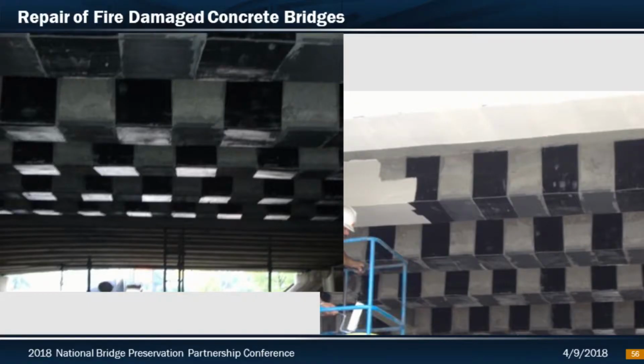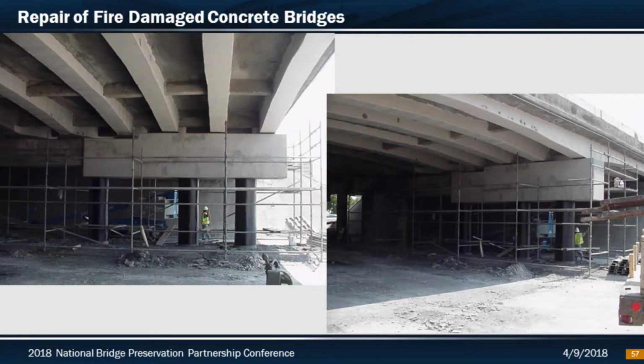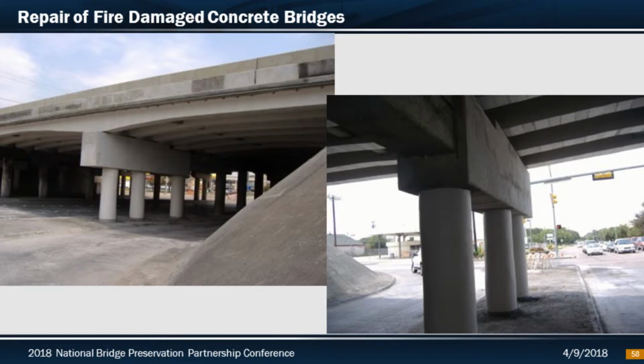Again, we go back to the saturator, and the pre-impregnation of the fabric sheets was employed on this carbon fiber job. It's, again, critical to make sure you get plenty of bonding resins, a good polymer matrix, as well as a good external bond to your structure. Getting close to the end with the cover top coat and the UV protection. Here's the completed project, which I think we could all imagine was a tremendous cost savings and a huge time reduction on the repair. It worked fairly well.